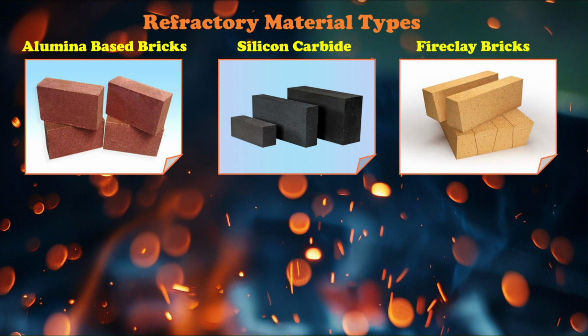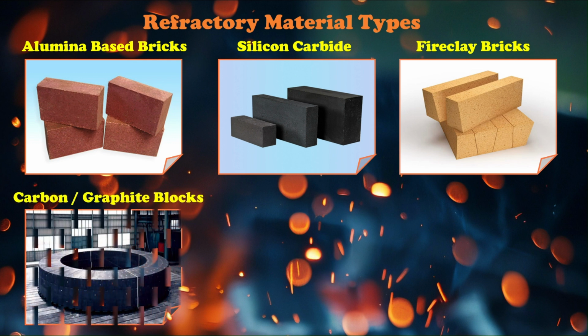Fireclay bricks, 39–42% alumina. Commonly used in the stack and belly zones to provide abrasion resistance and chemical stability at moderate temperatures. Often, Super Duty fireclay bricks are used in the stack. Carbon and graphite blocks. Widely used in the hearth and lower parts of the furnace due to their excellent resistance to molten iron and slag corrosion, high thermal conductivity, and thermal shock resistance.